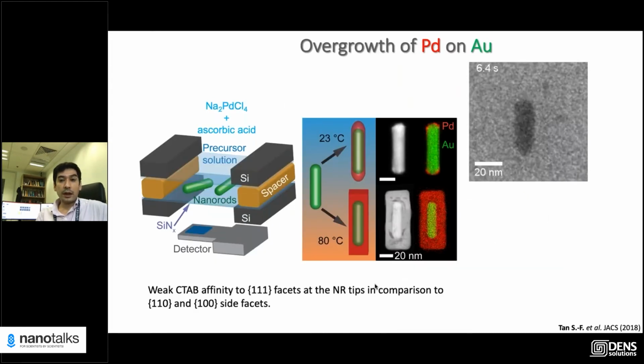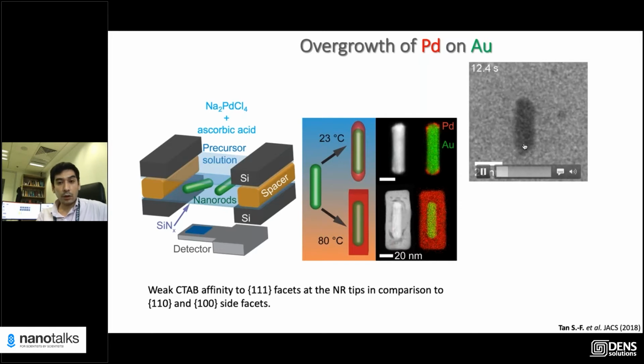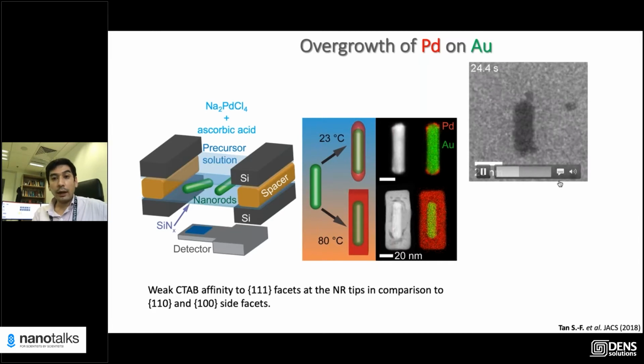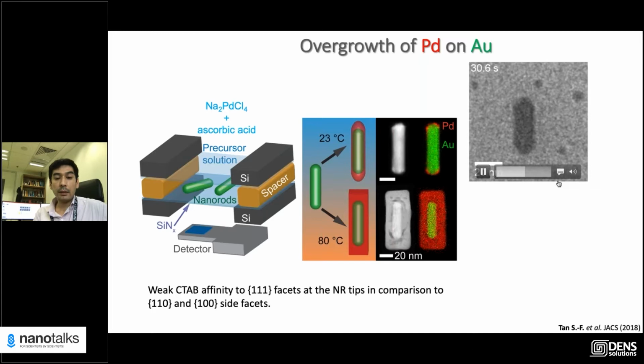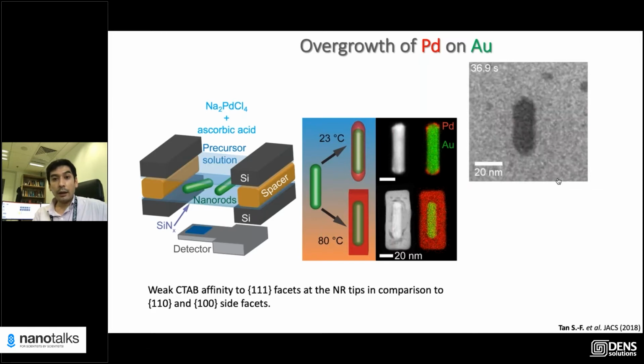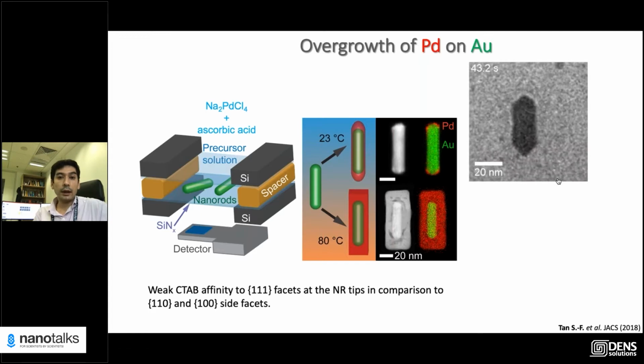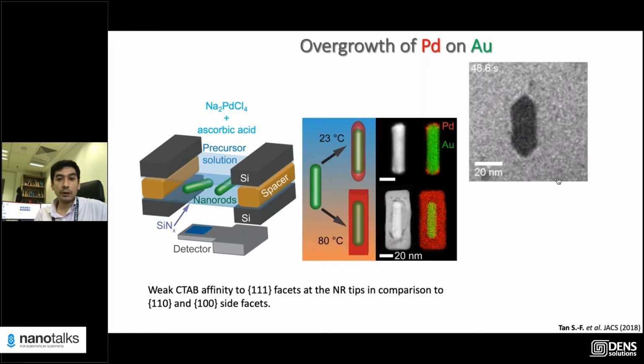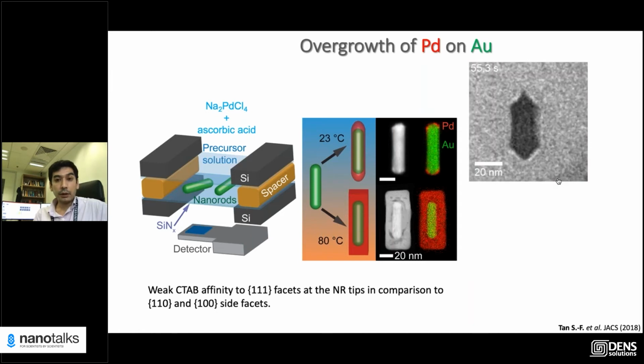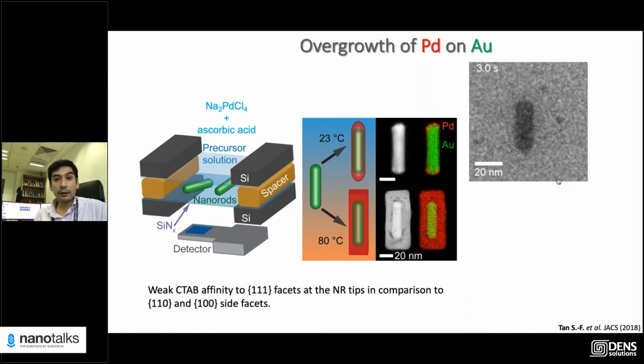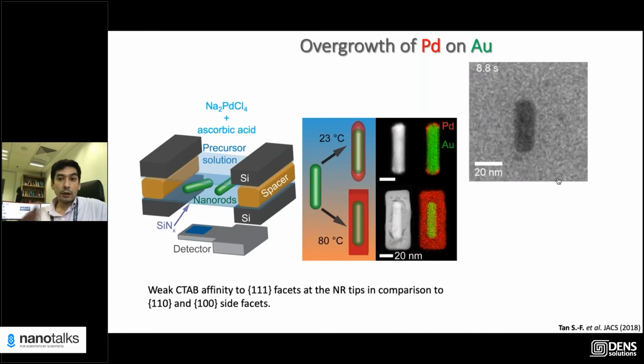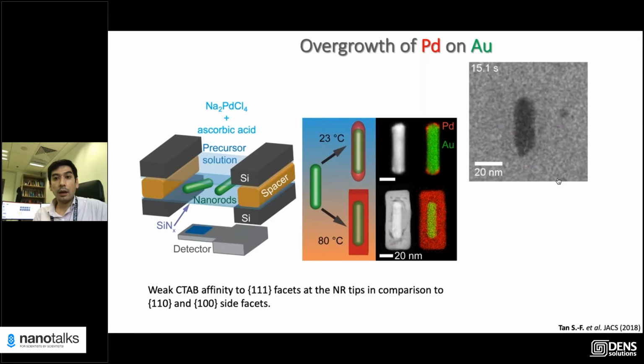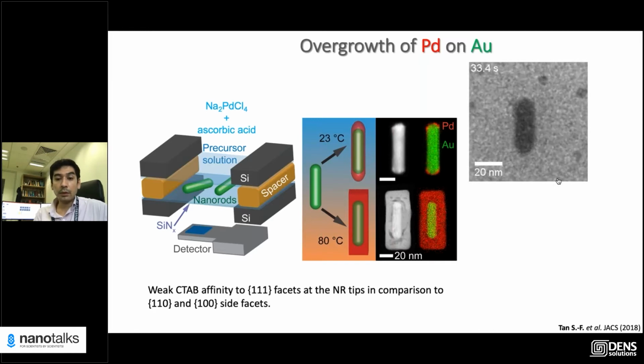So the room temperature reaction is very straightforward. You load your reaction solution, you load your nanoparticles, and you watch under extremely low electron dose to be careful that the beam does not affect your reaction. And you see how it actually evolves, right? It's depositing on the sides, but most predominantly depositing on the tips. The reason is that these nanoparticles are coated with surfactants, and the affinity of the surfactants to the tips of the nanorod is less, so they're less coated, and that's where most of the gold or palladium atoms from the solution deposit.